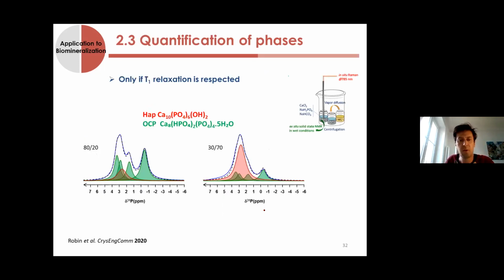When you pick up some spectra, of course, you can also make some decomposition of the spectra, and you can have access to the proportion of each phase. If you're looking at the spectra here, it seems quite complicated, but if you know the position of the line width, if you have the reference, it's quite easy to make a decomposition, which is quite precise actually.